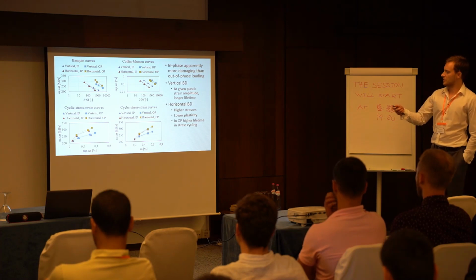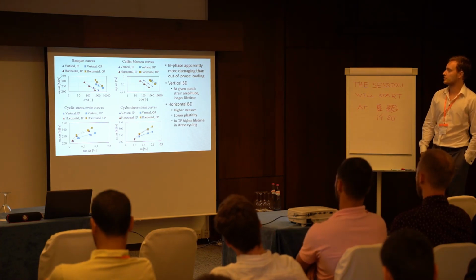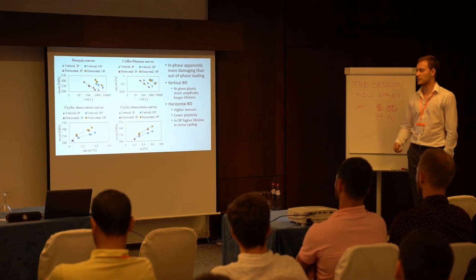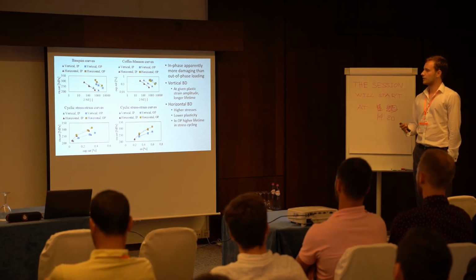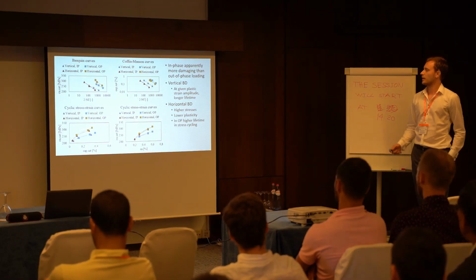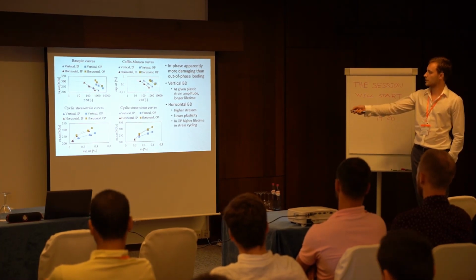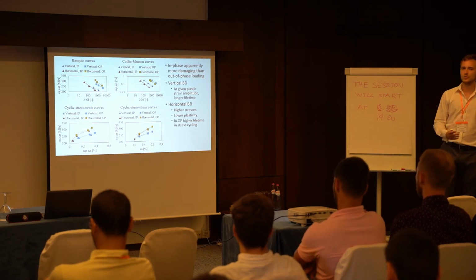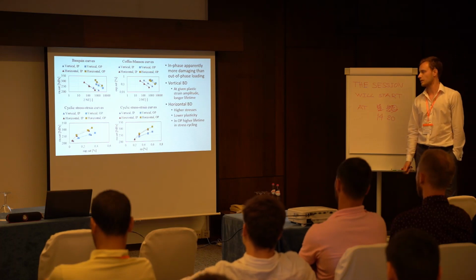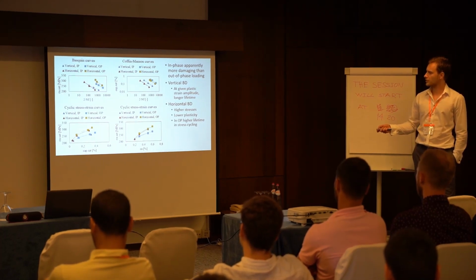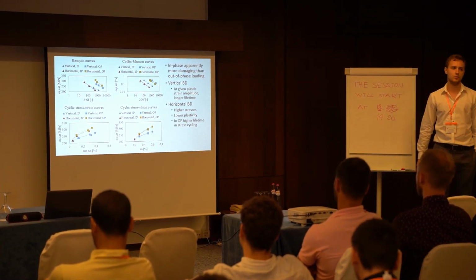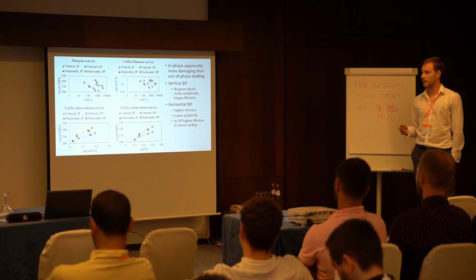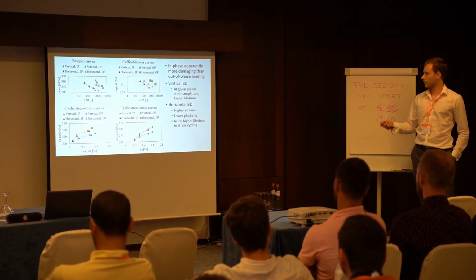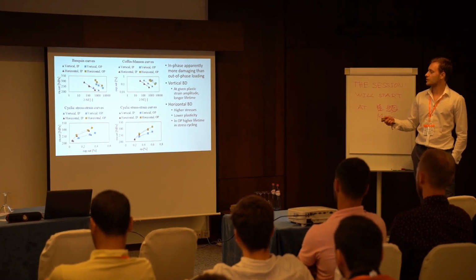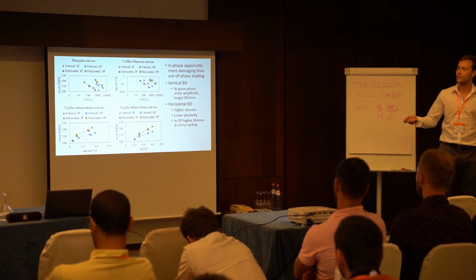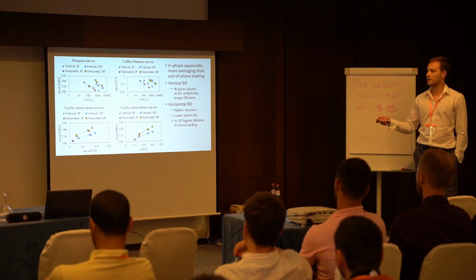Okay, so from the lifetime curves, it is quite noticeable that in-phase was apparently more damaging than out-of-phase testing conditions. Another feature we could deduce from the charts is that regarding the vertical building direction, as we see here, a given plastic strain amplitude leads to a longer lifetime comparatively to horizontal building direction. From the cyclic stress-strain curves, we can deduce that horizontal building direction was, on the other hand, linked with notably higher stresses and lower plasticity. Another thing we can notice is that in out-of-phase, should we test it in stress cycling, we would get higher lifetimes for horizontal building direction.